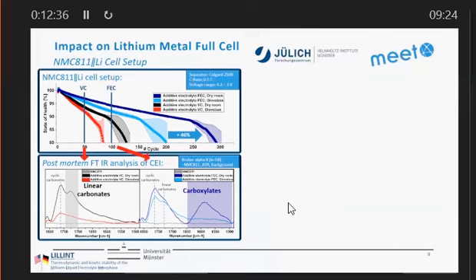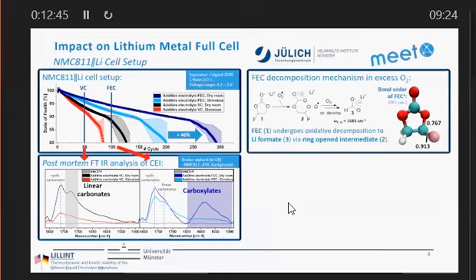So we have here a new species that is formed in the presence of dry air, which is not formed in the presence of argon in a glove box. And if we do simulations, we can see that carboxylates, for example formates, can form by FEC reaction on the cathode. So at the end, what we do in a glove box versus a dry room has an influence that is probably stronger than the influence of the additive itself. Just look at the difference for FEC in glove box and dry room, and the difference for VC in glove box and dry room. It is really an enormous influence.